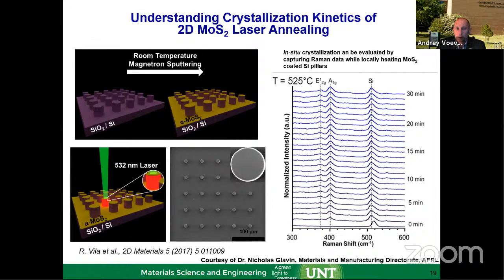And the way those autonomous experiments work is that the machine is programmed to deposit the heat of the laser on the surface to bring the temperature up by annealing, and monitor the temperature by Raman shift, and then check the in-plane and out-of-plane vibration for the crystallinity. Then the machine is set to find the optimum parameters by varying the gas composition or varying the power of the laser. In an autonomous way, running hundreds and thousands of experiments, it self-guides itself to achieve the highest sharpness of this in-plane, out-of-plane vibration, which gives you the highest crystallinity. Those experiments relate to the optimization of the annealing parameters: what the power, what the time is under this type of conditions.